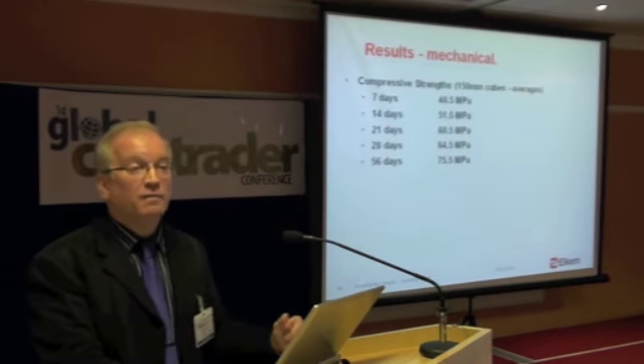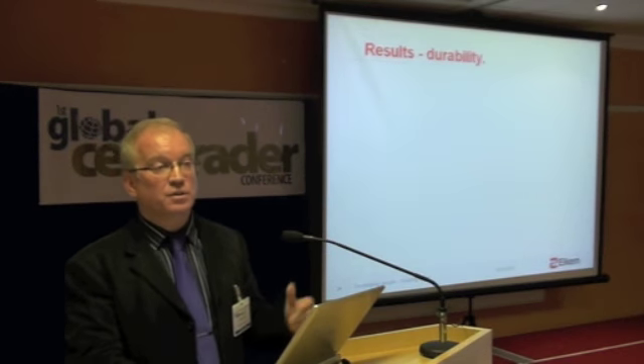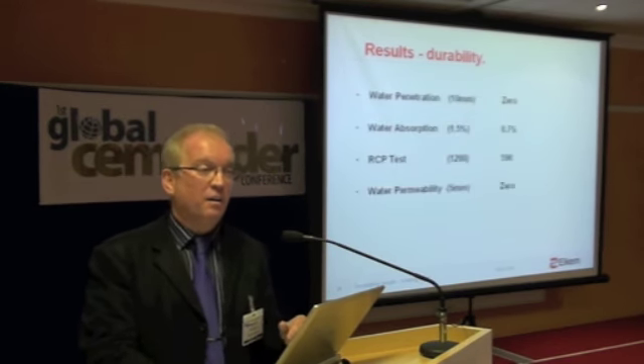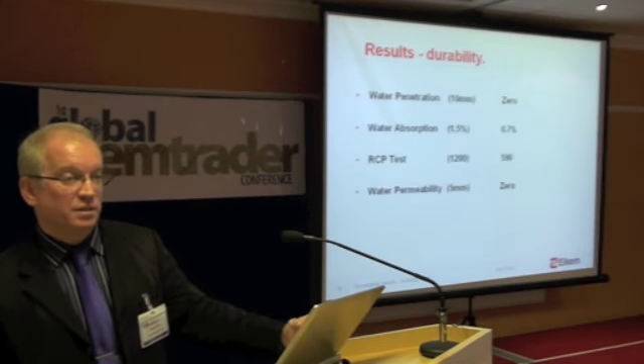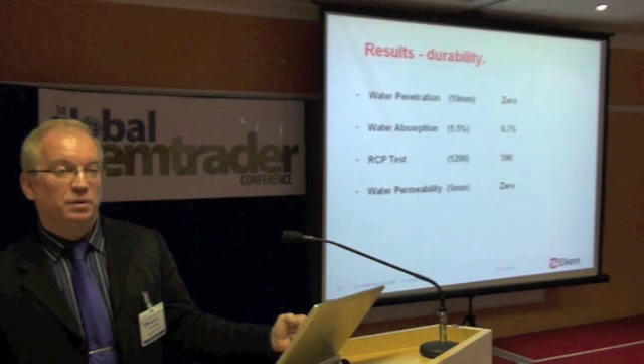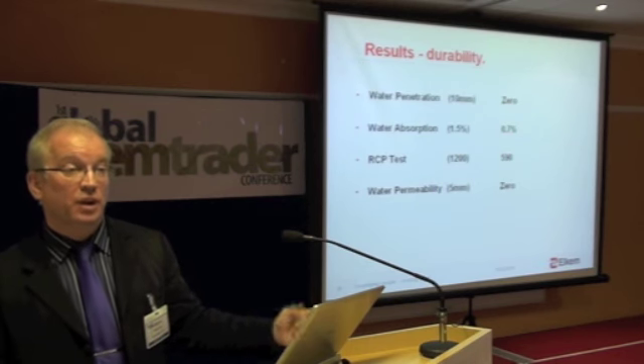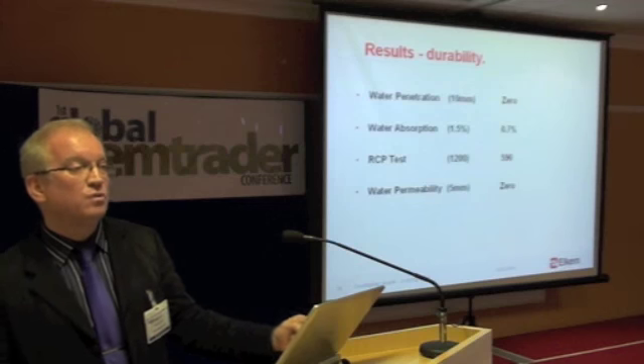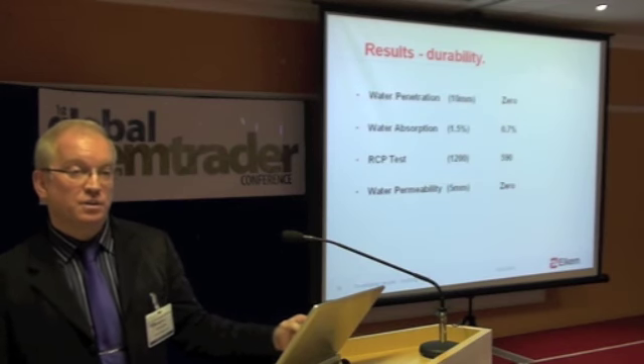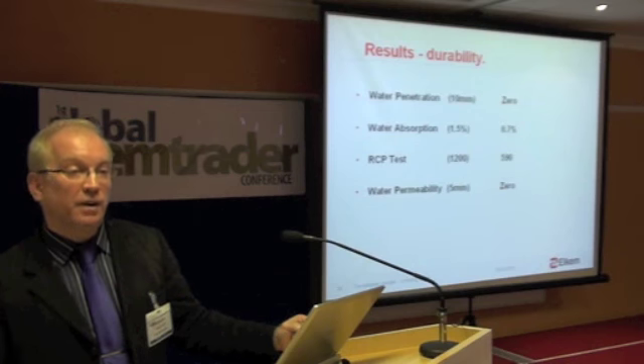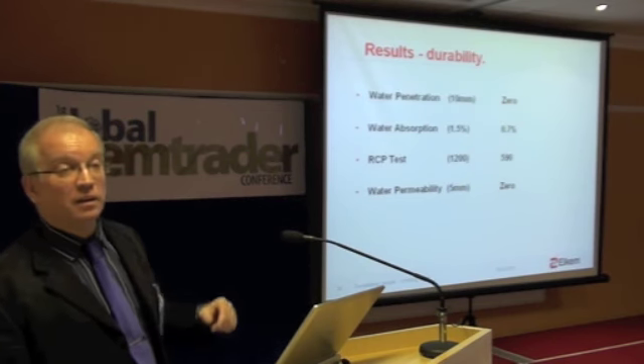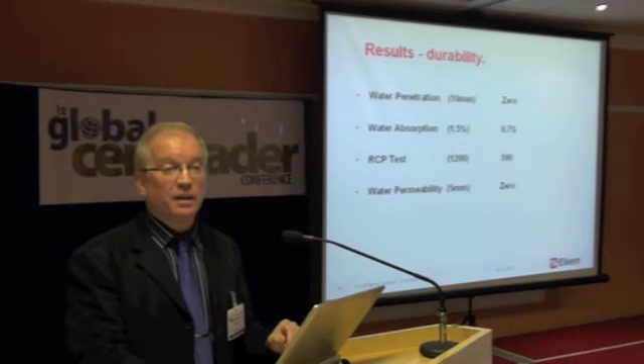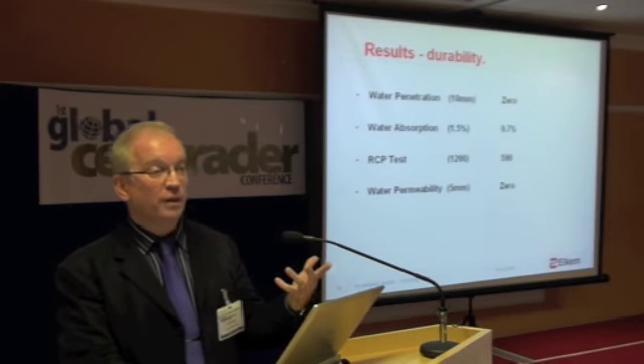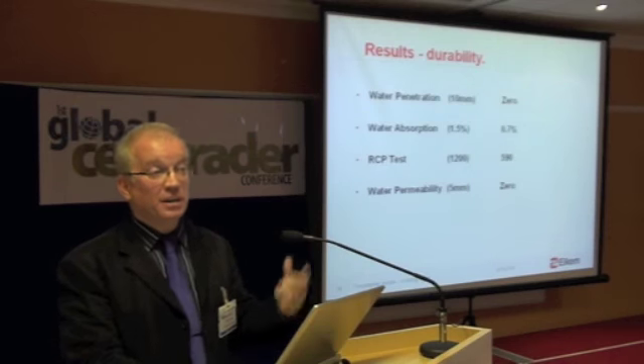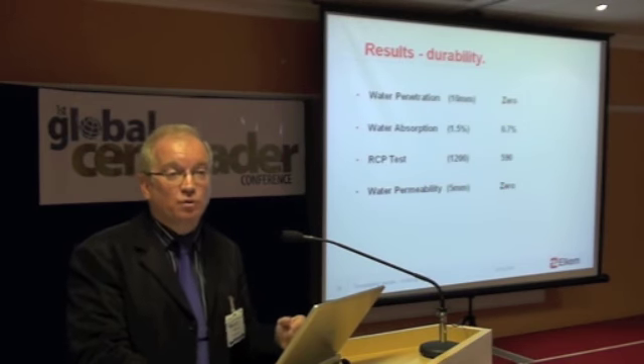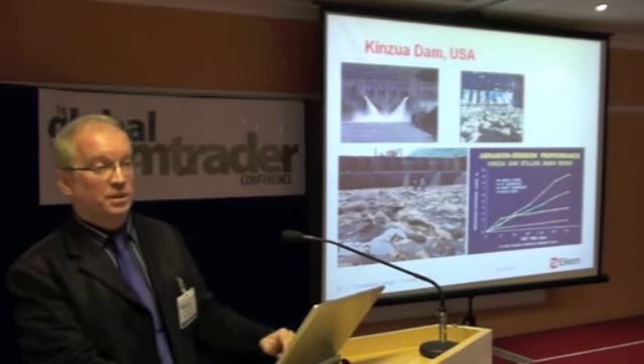How did we do? Very well. Exceeded the strength criteria, is not a problem. And there are your durability characteristics. 0 water permeability. 0.7 on the water absorption, cut in half. Less than 600 coulombs on the electrical resistance. Chloride resistance to very, very low levels, zero water permeability again. That is durable concrete. That's a triple blend to get the best. It needs to be the best. It's carrying the world's tallest building. They have to have that quality.